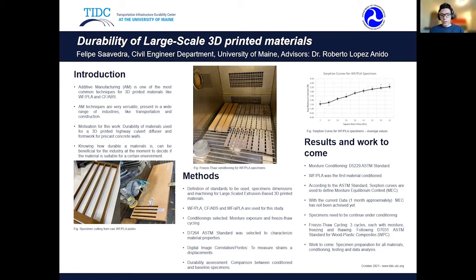Moving to the next point about results and work to come. For moisture conditioning, the ASTM D5229 standard was selected. Wood flour PLA was the first material conditioned. Why was this the first material? It was because it was the only material available at the moment. The parts for carbon fiber reinforced ABS were not printed yet, so there were no plates to be used. And also the wood flour aPLA just recently arrived to the center, so in the past few weeks they've been printing. So that's why wood flour PLA was the first material to be conditioned.